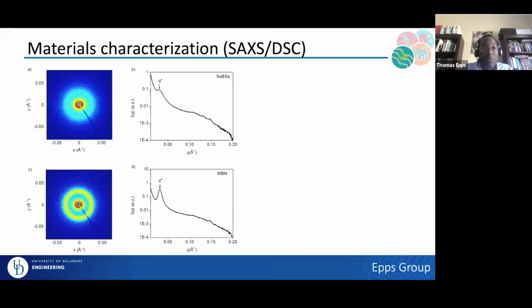I'm not showing the GPC data, but just suffice to say, we were able to make that block copolymer. We could show that we had chain extension to make this nice, we called it SABSA tri-block copolymer. And what I'm doing here, and you can see faintly the faint ring, there's a little bit less electron density contrast in this material, this bio-based material, than I see in the commercial base, which is a methyl methacrylate, butyl acrylate, methyl methacrylate tri-block copolymer.